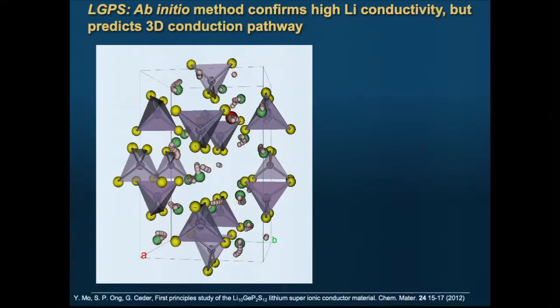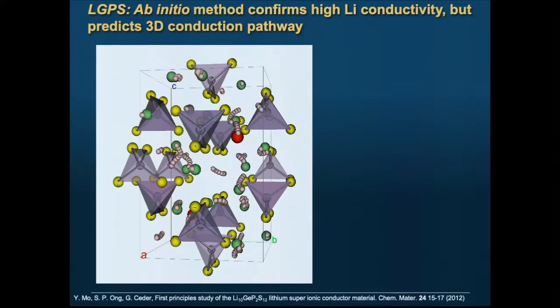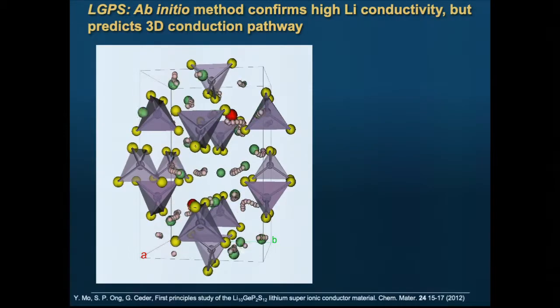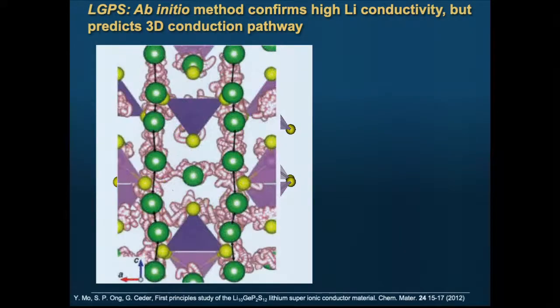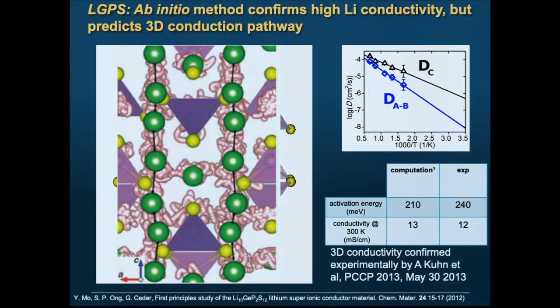We jumped on that right away and did ab initio simulations. This is just a pretty picture where we show that indeed you have very high conductivity. But we showed, and this has been confirmed by others, that it's not a one-dimensional conductor, that it's a three-dimensional conductor, because you have diffusivity in all 3 directions. And that makes sense. One-dimensional conductors are terrible because they have channel blockage. Even fast one-dimensional conductors tend to not operate in a macroscopic mode, because anytime you put a defect in the channel, it is completely blocked.